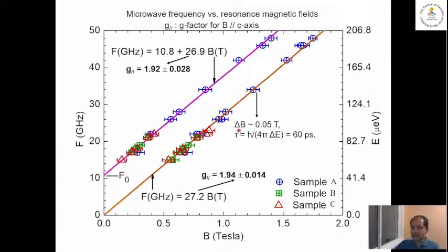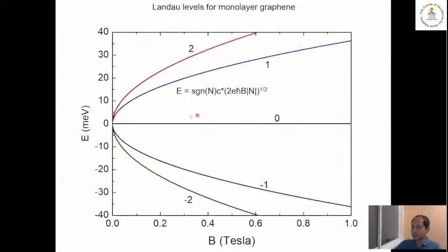Question is, how do you understand that? Turns out that these are the Landau levels for graphene in the magnetic field. In electronic systems, if you apply a magnetic field, you get these highly degenerate levels called Landau levels. Usually those levels are linear in the magnetic field, but for a linearly dispersed material like graphene, it goes like the square root of the magnetic field instead of linear. It also depends on the Landau level index as the square root of the index. So these are Landau levels for graphene.